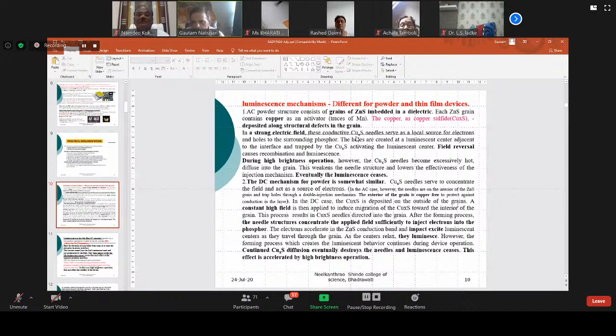Okay, DC powder is similar, but there is a difference. In DC, copper is outside the grain. Copper is separate. It is not in the host grain. Then a constant high field is applied to induce migration. This process results in copper needles directed to the grain. The needle structure concentrates the applied field sufficiently to inject electrons into the phosphor. The electrons accelerate in the zinc sulfide conduction band, then they hit the luminescent centers. By impact, with high velocity, the luminescent center gets excited and then emits light. Then continued copper diffusion eventually destroys the needles and luminescence ceases. I mean, in DC high brightness operation, DC cannot be used.